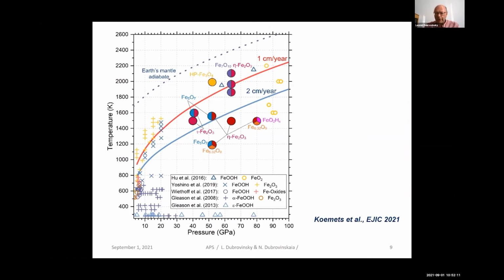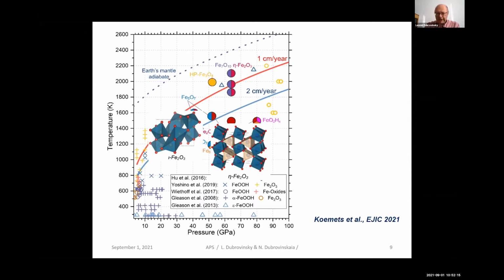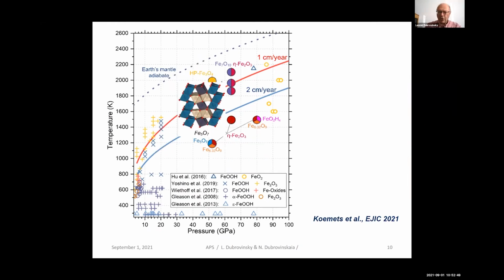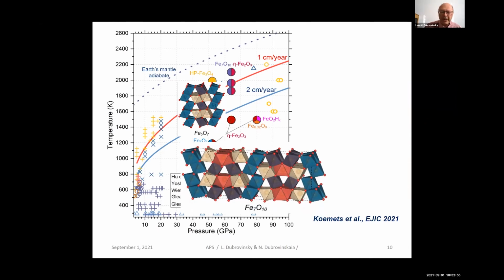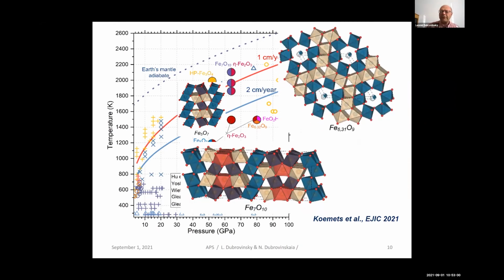Now, what we have seen. First of all, we found that if the temperatures are not really high, let's say on the level of or below the super cold geotherm, we observed the known Fe2O3 phase. If you go much higher in temperature, somewhere above the cold 1 centimeter per year sinking slab geotherm, we start to observe the high pressure Fe2O3 phase. But we also see the formation of mixed valence iron oxides, known ones like Fe5O7, or some new ones like Fe7O10 or Fe6.3O9.